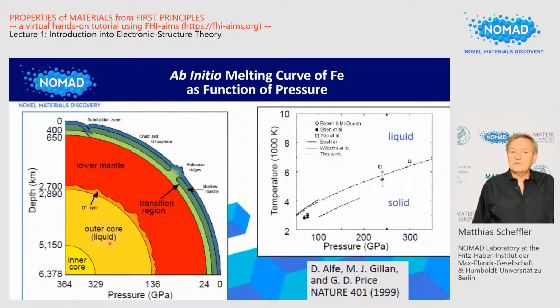Of course, there are also some uncertainties in the theoretical results. These uncertainties arise because a somewhat small supercell was used, the exchange correlation functional was treated approximately, and the authors studied pure iron, that is, without oxygen, sulfur, and so on fractions. That must be there as well. They have later, in fact, refined these calculations. Altogether, the uncertainty of the calculated viscosity may be a factor of 3, but this is still much lower in uncertainty than that of the experimental studies.